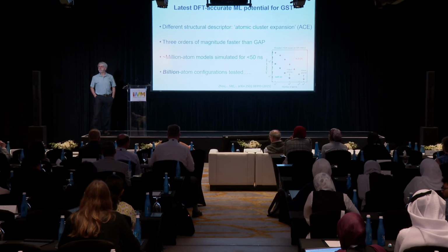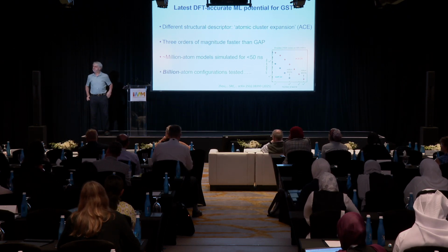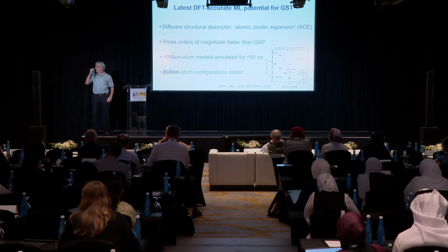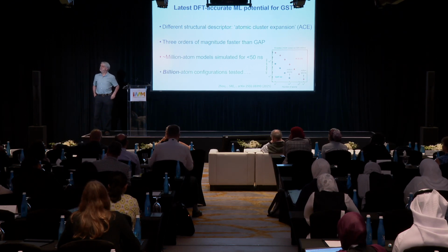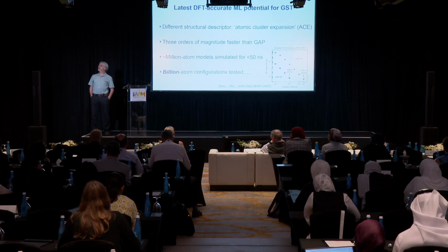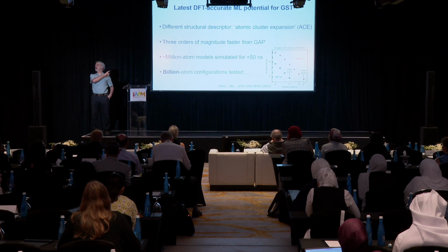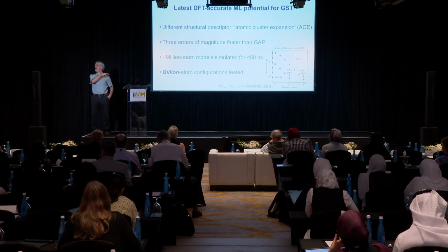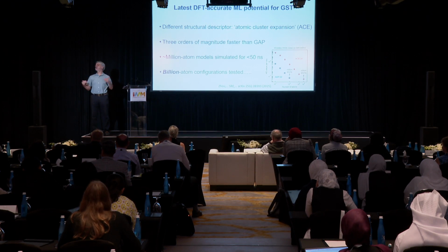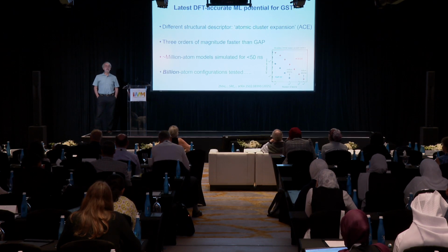The business you showed about the nucleation of the left and right-handed and the grain boundary, that is effectively a soliton. So it doesn't require a lot of energy to move, and that's why you eventually see it crystallizing out. If you use a one-dimensional model or a few dimensional models, it maps onto a soliton, moving up and down. We found that you're only 90 meV per atom higher in the cube than you are in the chain, so it's a very low barrier.